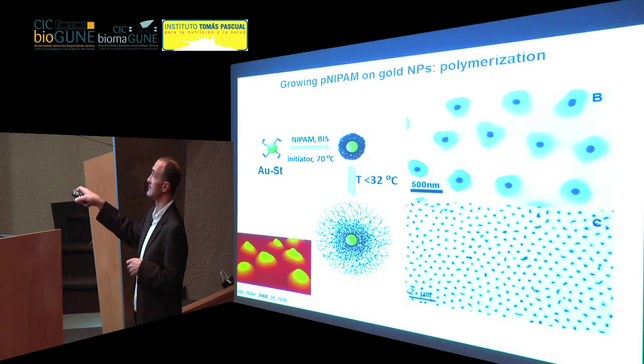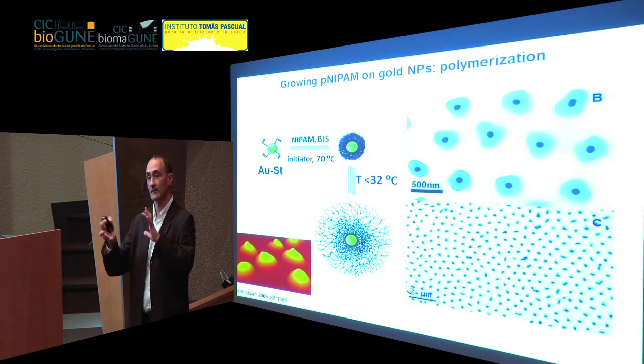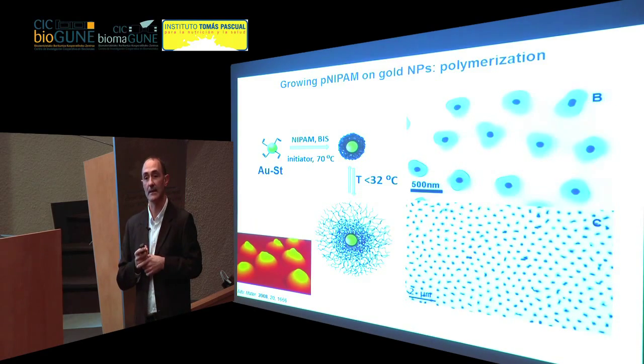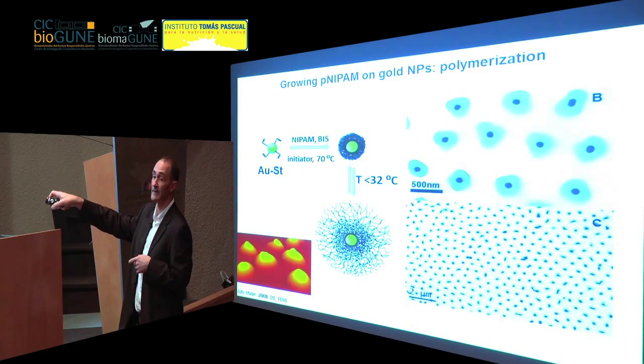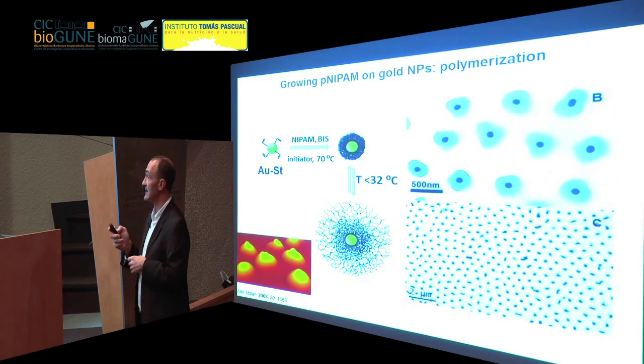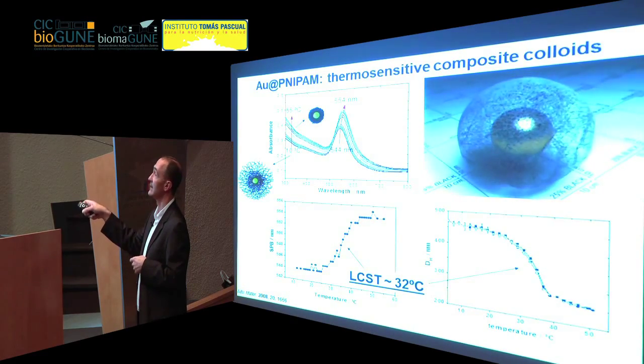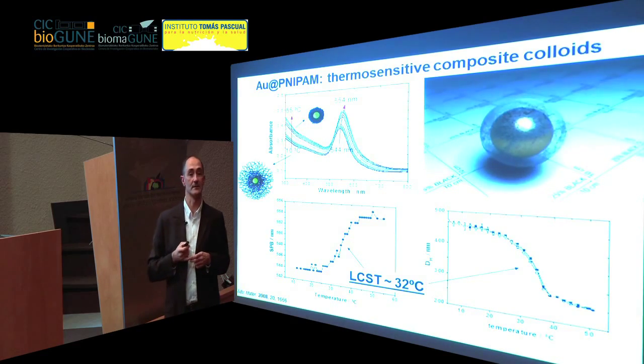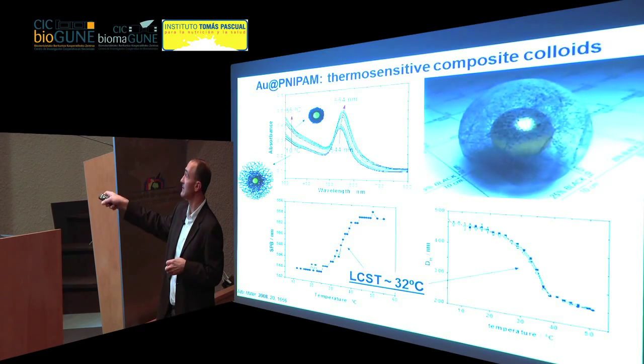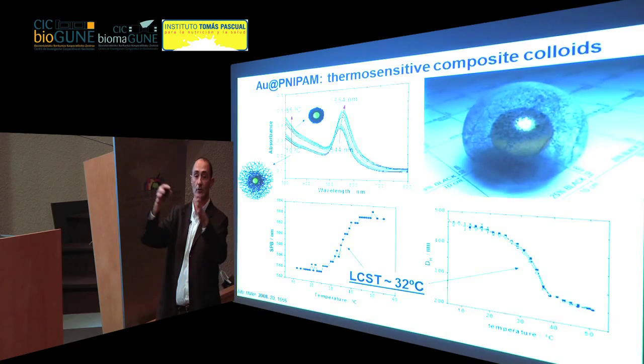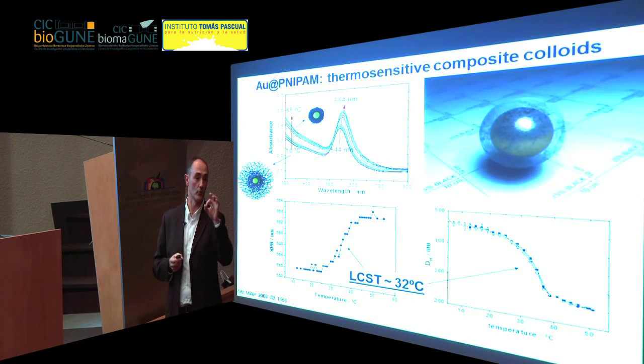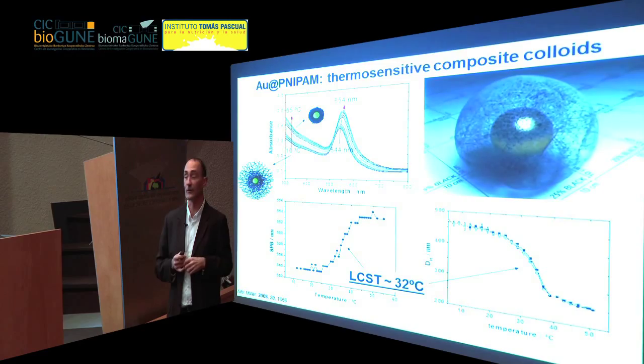This is because this is actually, so to say, a fluffy system, which when you dry it, it actually collapses on top of the metallic particle. And this is what you see here also in the AFM picture, where you see that the gold core protrudes out and the polymer is actually flattening around it. But in solution, we expect it to be something like this. A fully concentric system where by changing temperature it can be expanded or collapsed only in the shell, and the core is of course not changing because it's made of gold.